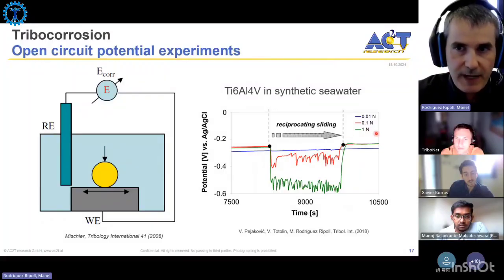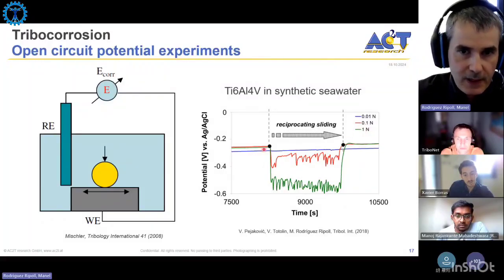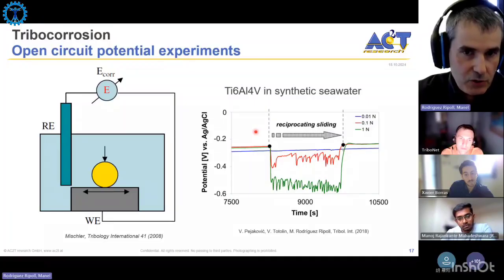And if we apply a higher load, then we fully depassivate the material. The material remains almost fully depassivated, more or less constant throughout the experiment, and at the end of the experiment, the open circuit potential returns to the equilibrium potential that occurred before sliding. So this is something that you can learn, for example, by monitoring the open circuit potential.